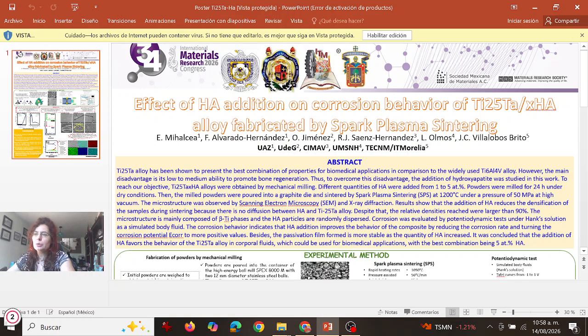Corrosion was evaluated by potentiodynamic test, under Hank solution. We use that as a simulated body fluid. The corrosion behavior indicates that the hydroxyapatite addition improved the behavior of the composite, by reducing the corrosion rate and also turning the corrosion potential, the Ecorr, to a more positive value. And besides, a passivation film is formed, and it is more stable as the quantity of hydroxyapatite increased.